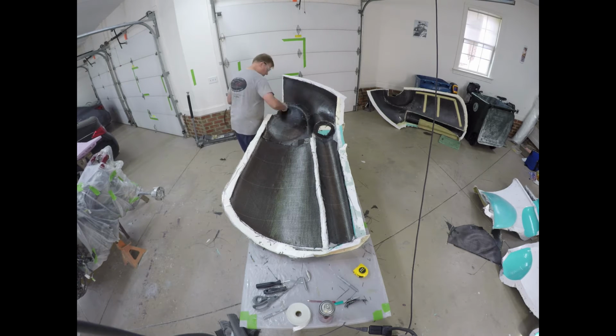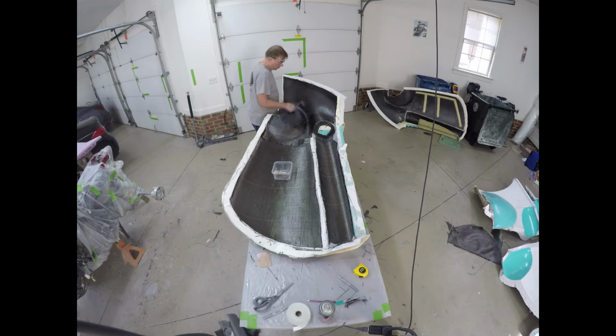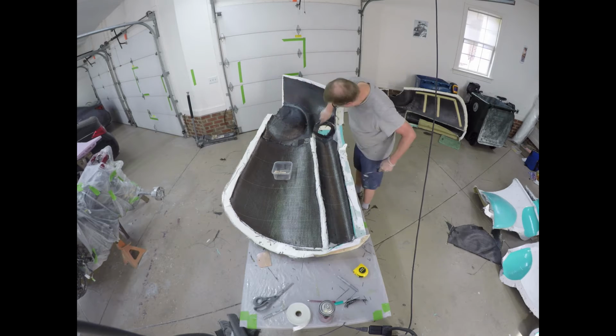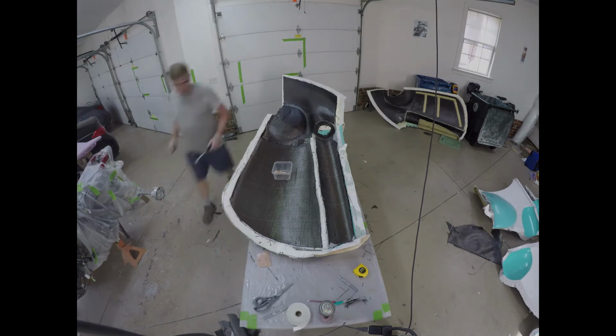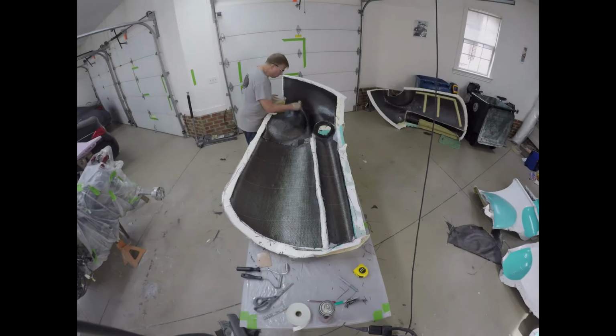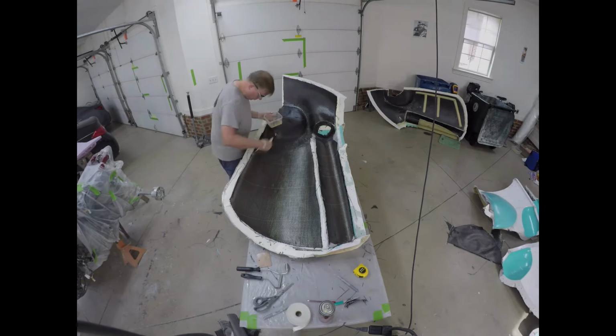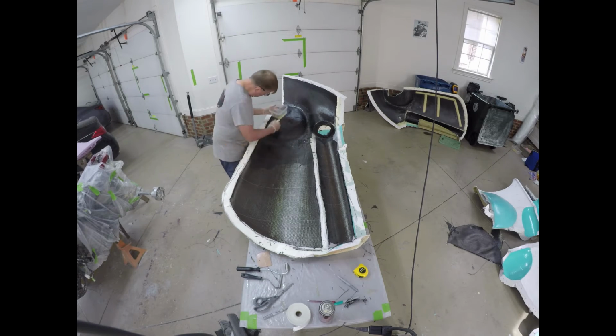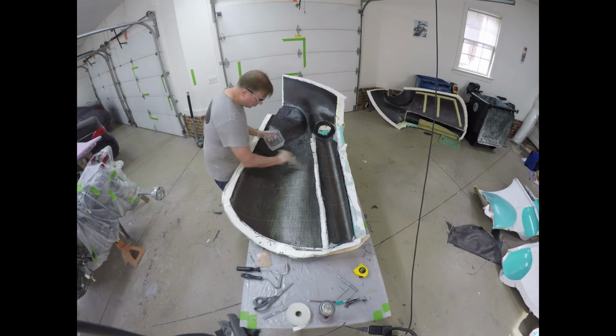And just really soaking this. Remember, I've got 2 layers of 6-ounce carbon fiber here. And along that sharp curve, I've got 3 layers of 4-ounce fiberglass. So you really, really want to soak it here to the point where you have excess laying on top of the fabric. Should be shiny everywhere.